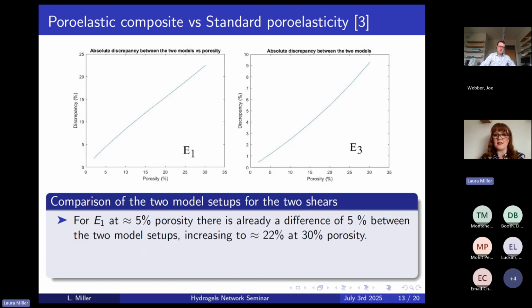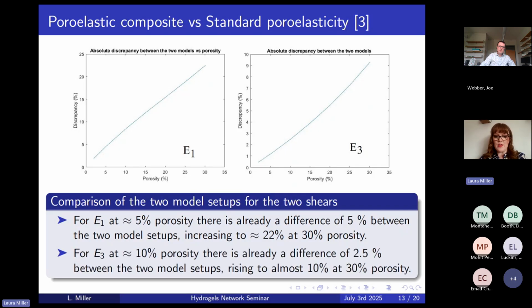So that therefore means that the comparative case that we feel was the best possible comparison wasn't really working for those types of materials. And similarly, again, with E3, we were seeing maybe a slightly less discrepancy, but still incredibly significant. At 10% porosity, there was already a difference of 2.5% between the models, rising to almost 10% difference at 30% porosity.